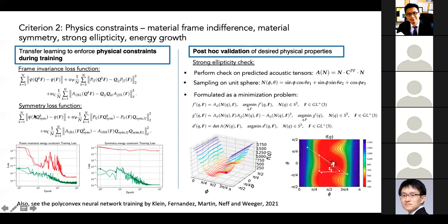And then similarly, the symmetry requirement. A lot of the time when we train a constitutive response, we may directly use the invariance approach to create an energy functional that has the right symmetry and also makes the simulation easier because we probably will have fewer inputs. But for very generic predictions, you can impose the symmetric loss functions. Shown here is the comparison of incorporating the symmetric loss functions in the supervised machine learning problem and not putting it in. You can see that if you don't enforce it, even though the material data has symmetry, in this case monoclinic, the resulting prediction loses the right material symmetry, which could be a problem in the numerical predictions.